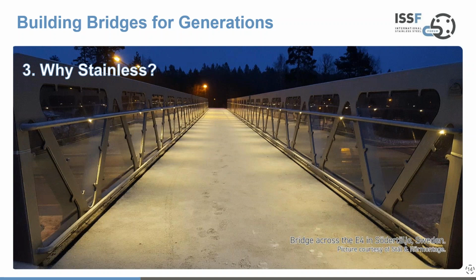A duplex stainless steel, as I mentioned, will be quite comfortable down to about -50 degrees centigrade. The austenitic family of steels doesn't suffer that ductile brittle transition, so can go much lower in terms of operating temperature. Of course, you're going to get through a freeze-thaw cycle some material expansion and contraction issues, and they would have to be factored in at the point of design. But I think the real problem is how you cope with what happens to the operation of the bridge during the periods of freezing, and then how that's addressed. And I'll come on to explain that in a few moments.